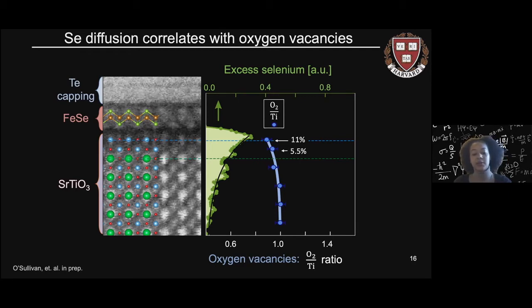It's also important to note selenium belongs to the same chemical family as oxygen, and so this could be a reason the selenium is able to replace the oxygen vacancies, whereas the iron, which also resides in the monolayer, is not able to.